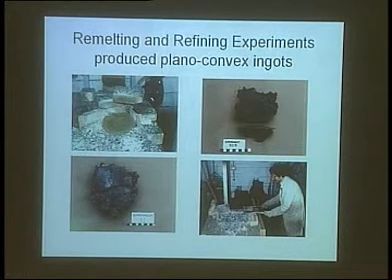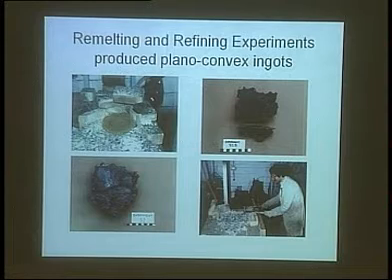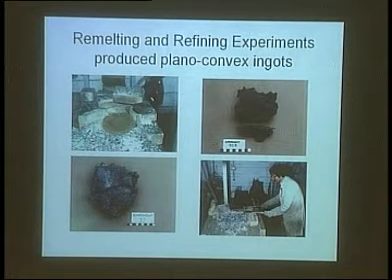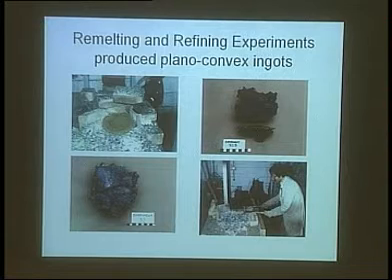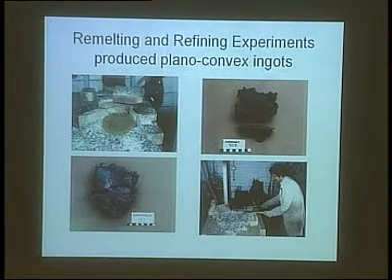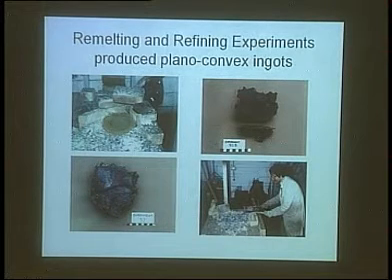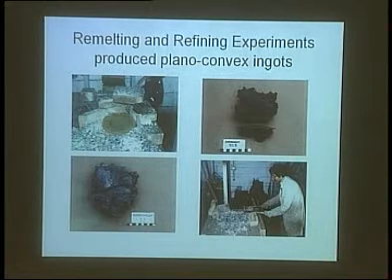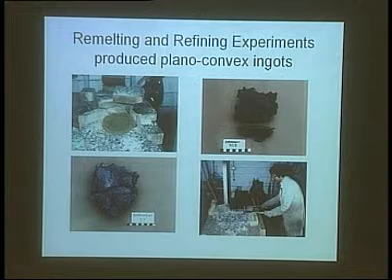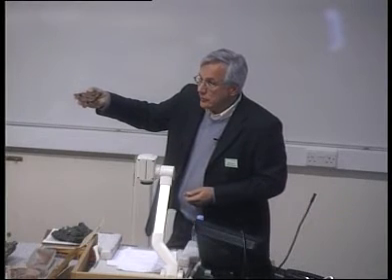We found that on remelting the copper under partially oxidizing conditions, with not such a blue flame as before, because it's harder in a shallow hearth to get such reducing conditions, the slag that developed on the surface was very iron-rich. That was coming from the iron in the copper, reacting with oxygen and other fuel ash. So that was the crucible slag. Every time I remelted the copper, it improved in quality.